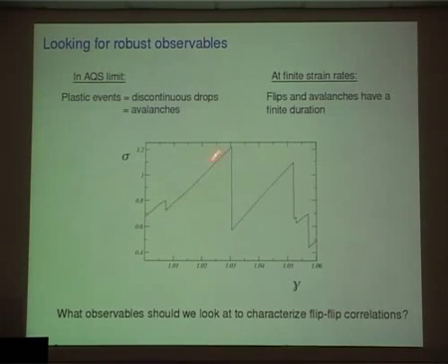Now, the point here is that as soon as you start to go at a finite strain rate, if you look at your stress versus strain curve, it will start to show some kind of thing like this. And this occurs because, you remember I showed you that the energy descent is very intermittent. Very intermittent means that there are times when nothing happens, or barely. The system is not stable, has not found a minimum, but waves are just propagating, and there is no dissipation.